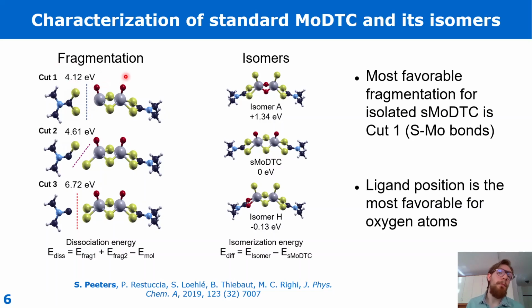We must remember, however, that a metallic substrate can indeed stabilize the molecular fragments differently, and so the picture can change. We then consider all the possible isomers obtained by exchanging the position of sulfur and oxygen. It turns out that the bridging position between molybdenum atoms in the compound is the least favorable for oxygen, while the ligand position between carbon and molybdenum is the most favorable.